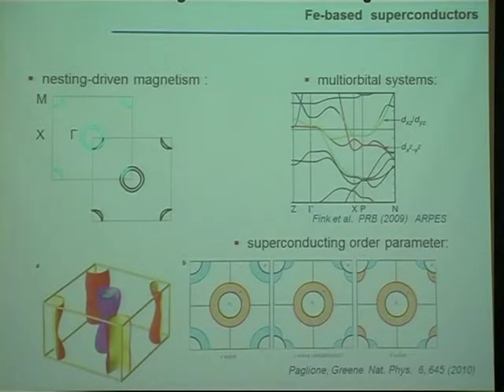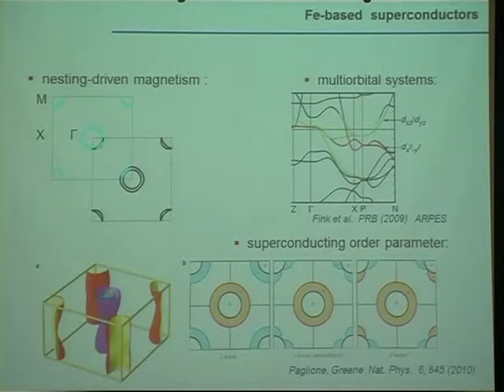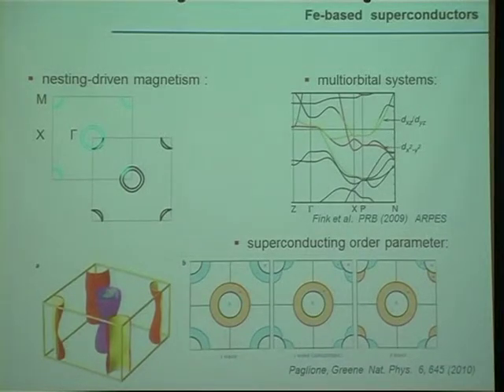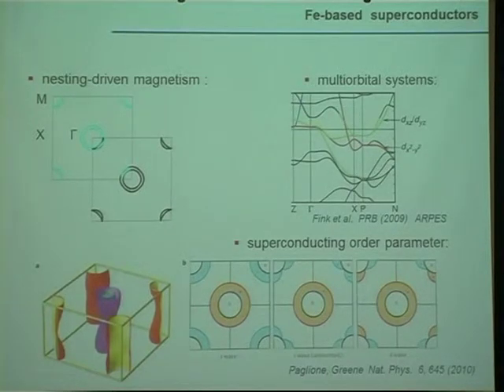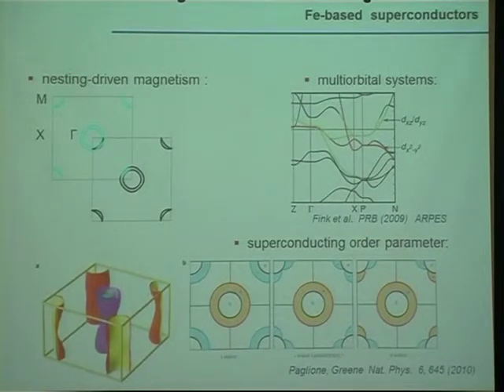What is universal about these materials — and again different from the cuprates — is that we are dealing with multi-orbital systems. In the cuprates, we have the x²–y² copper band and have been living for many years with the one-band Hubbard model. Now we are faced with a multi-band system and have to take care of all the physics coming from these multiple bands. A second issue, very much discussed at the beginning, is that the band structure of most of these materials shows nesting features, and the spin density wave can naively be explained as originating from nesting effects. There are new classes of materials that don't show nesting properties, so the importance of nesting for superconductivity and magnetism has become an open question.